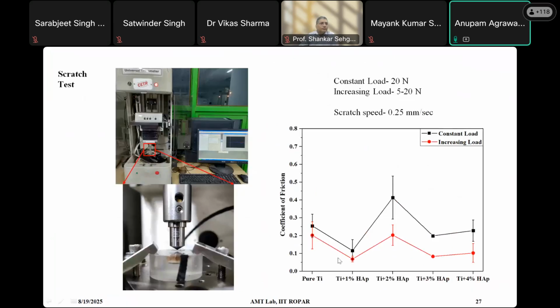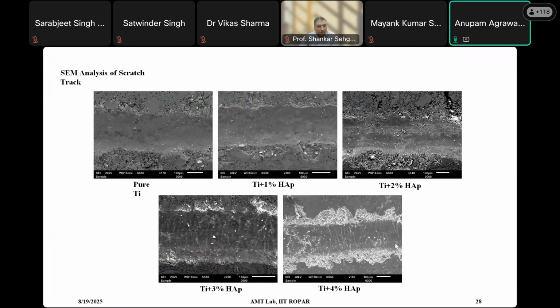So, a scratch test for different ratios of titanium and titanium hydroxyapatite. We found that it is almost as good as commercially pure titanium, barring 2% HAP, where the coefficient of friction was quite high, maybe due to some error in our mixing of that sample. So we analyzed the scratch test track, the wear track, and then